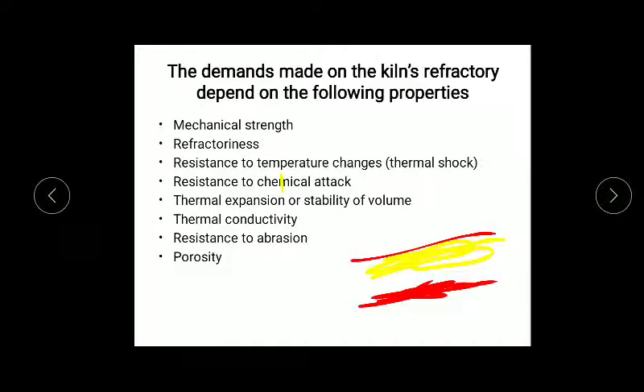Now in rotary kiln, what is happening is all the refractories except for this part are exposed to hot kiln gases, right? And only this part of the refractories is covered with the kiln feed. Hence all these refractories which are exposed to these hot gases are at very high temperature, and only these refractories are covered with the raw material and hence are at low temperature. And since this is rotating, these refractory lines will keep interchanging. Now this will go upside and it will become hot again, and this hot refractory lining, when it is covered with the feed material, it will get cold.